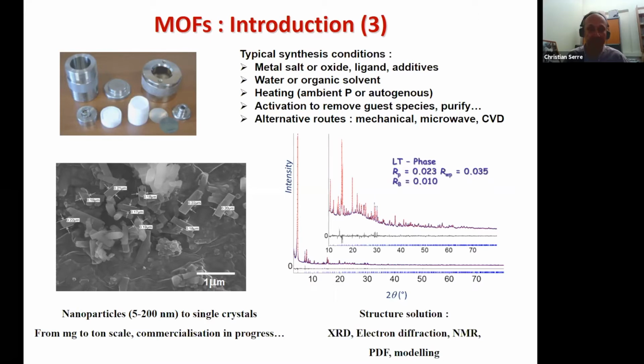What do you get at the end? You get particles. They can be nano, they can be micron size. And then, of course, you want to solve the structure of this. And you can use all the state-of-the-art techniques that are available, from laboratory single crystal structure down to powder diffraction, and then electron diffraction, which can be precession or rotating diffraction.